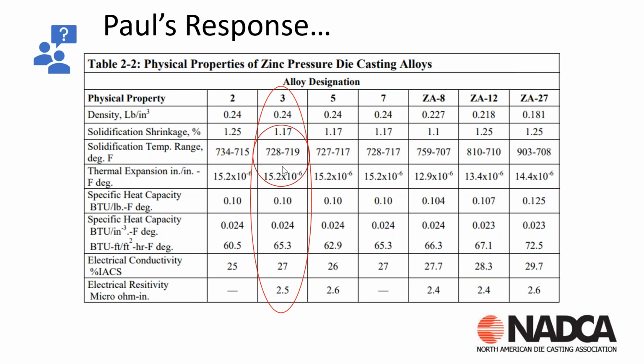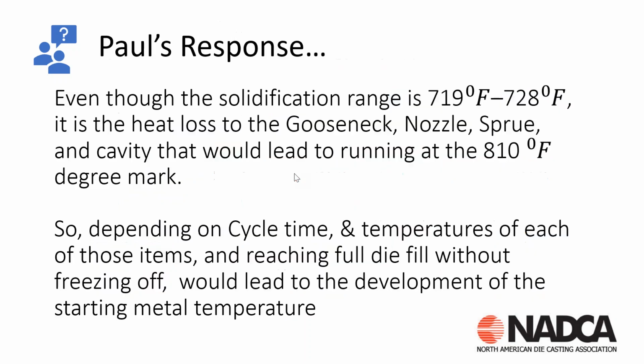And then when we're looking at this chart, we're singling out a Zamac 3, and then we're specifically zoning in on the solidification temperature range. So that solidification range is 728 degrees to 719 degrees Fahrenheit. That's where solidification is going to take place in zinc alloys. So even though we have this 19-degree range, when we're die casting the alloy, if we tried to cast at 719 or even 728 degrees, we're going to lose temperature.